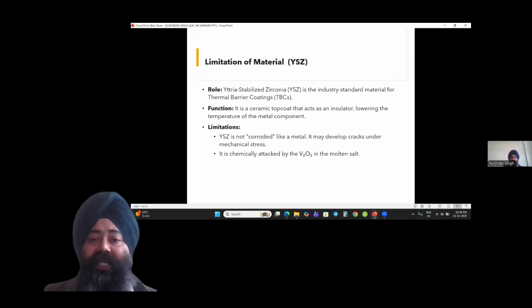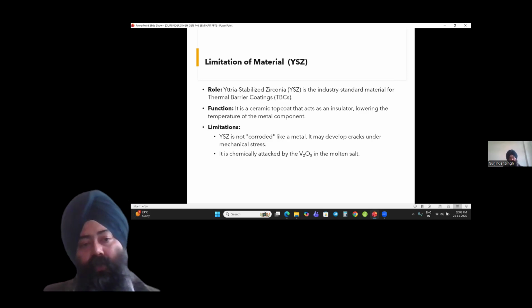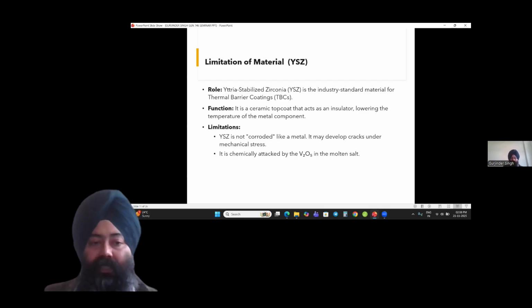It is the industry standard material for thermal barrier coating, YSZ. Its function is to act as a ceramic top coat that acts as an insulator, lowering the temperature of the metal component. What are the limitations when you use YSZ alone? It is not corroded like a metal, but due to mechanical stress, it may develop cracks. It can also be chemically attacked by V2O5 in the molten salt.